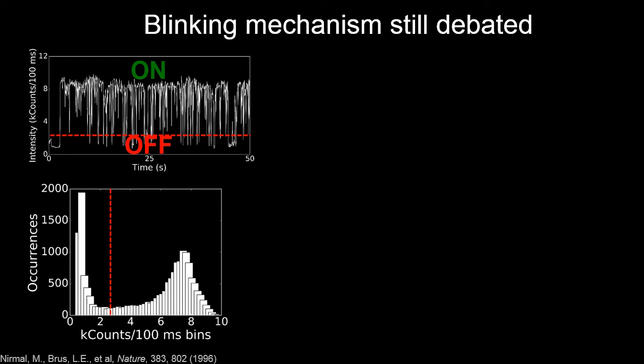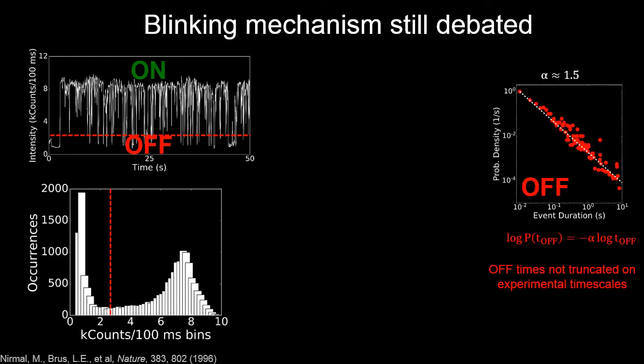After thresholding, we find the frequency of the durations of each on and off event and plot them to generate a probability distribution. If we plot the probabilities in a log-log plot, we get something unexpected. Typically as physical chemists we're used to working with exponentially distributed quantities and first order kinetics, but instead we see something that looks like a power law and extends over many orders of magnitude in time and probability.